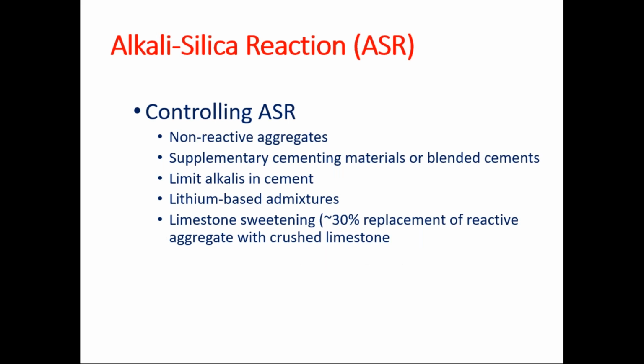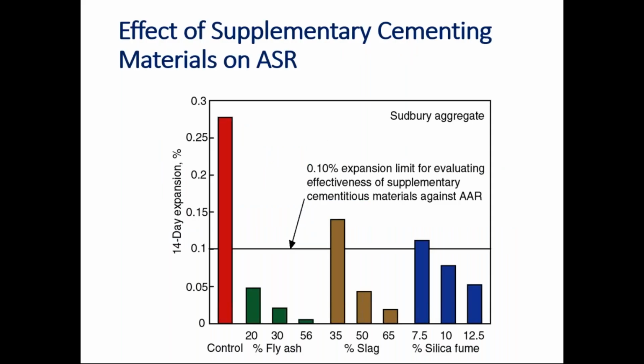How to control alkali silica reaction? Non-reactive aggregates you should use, supplementary cementing materials or blended cements you should adopt, and limit alkalis in cement. Lithium-based admixtures can be used. Limestone sweetening, that is 30% replacement of reactive aggregate with crushed limestone. So this is how we can control the alkali silica reaction.